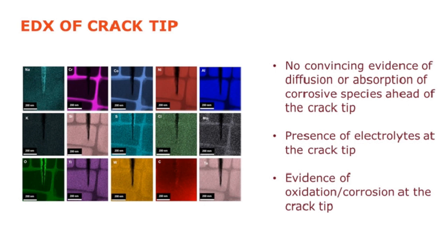So you can see we've got sodium there right down at the crack, so top left. If we have a look along, we've got our alloying elements, and you can see how they segregate between the gamma and the gamma prime. Quite interesting. Nothing too controversial there other than the tungsten in orange, which we found in the gamma prime, and I think that's slightly debated, but certainly we see it. We've seen it more in the gamma prime. We've also got oxidation going on right down the crack. So in green, the bottom left, we can see how oxidation is happening right down at the crack.